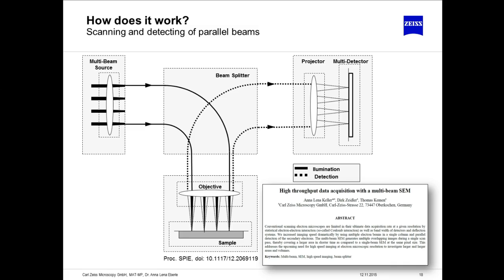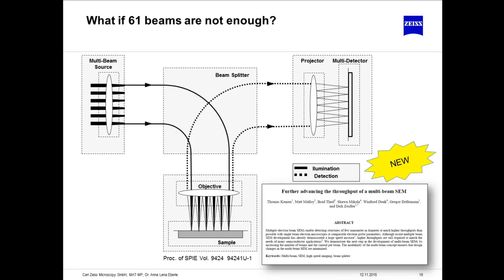Okay, this gives you an idea of how such a multi-beam electron microscope works. But what if this is just not fast enough? Now, there's a solution for that. You just add more beams. So it's a highly scalable technology. The 61 beams were just the first step. There's a 91 beam tool available now, which is just adding one additional shell of beams to the hexagon. And this is a tool variant that was just launched very recently, about a month ago, at the Neuroscience meeting in Chicago.